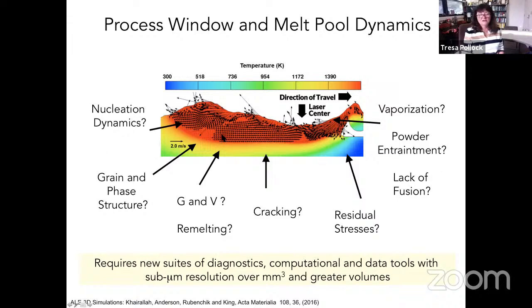Well, there's the nucleation of solid from the liquid phase and the formation of the grain structure. One has to worry about the gradients and velocities at which these interfaces are moving, the degree to which you remelt material below when you scan the beam across, the potential for cracking, residual stresses, lack of fusion, what happens to that powder, and how much of the material is vaporized. And so what we've been trying to do is really understand a lot of these details at the scale of the melt pool. And so this is sort of at the scale of cubic millimeters.